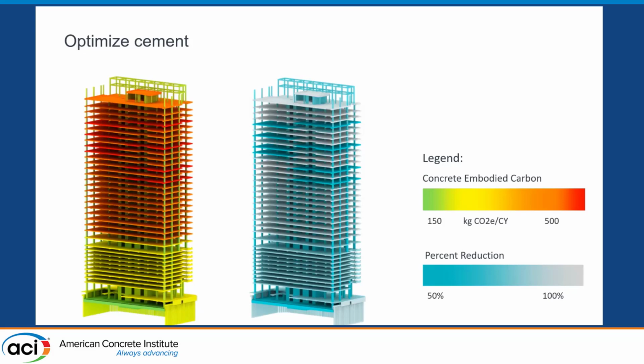In this case, there were some post-tension floors, and so more cement was needed at an earlier age. And so if you can imagine that you have a cement budget and you think of where you need it the most and what elements can have higher cement replacements or alternatives, the LCA can be used to understand how best to optimize cement for different elements. So if you take a data-centric, element-based approach, it can lead to much more carbon-efficient designs.